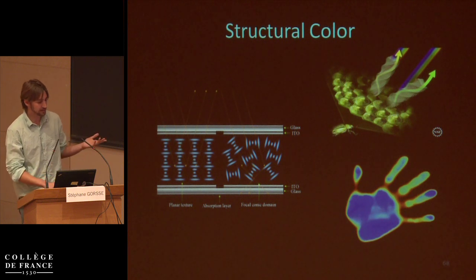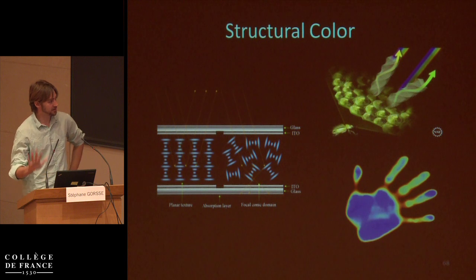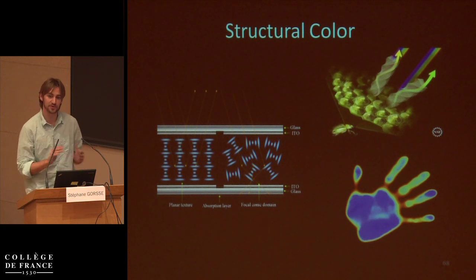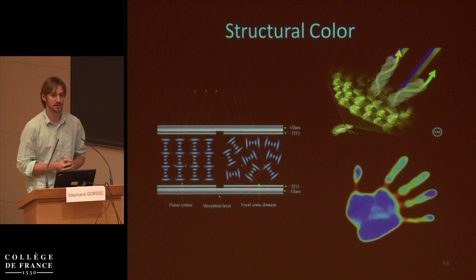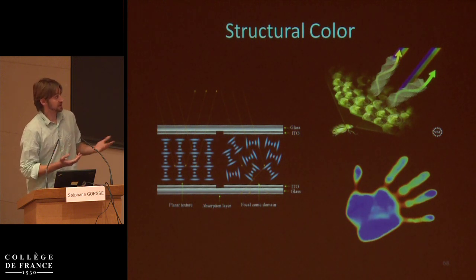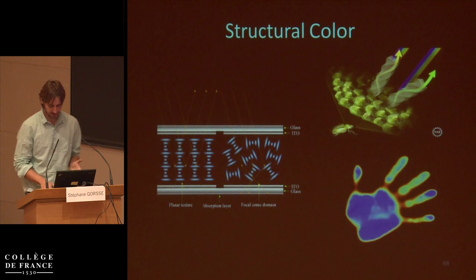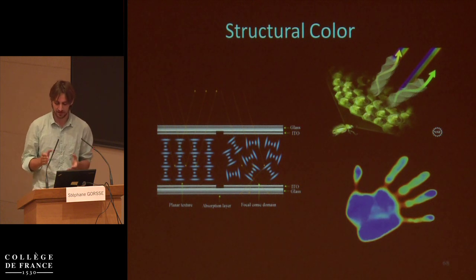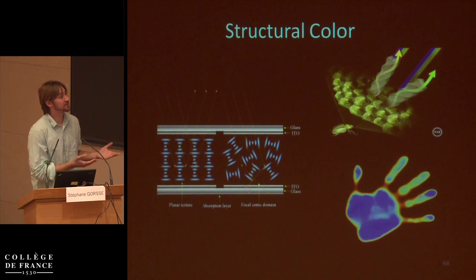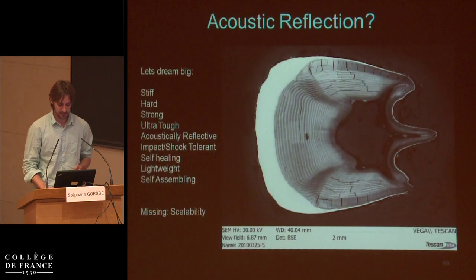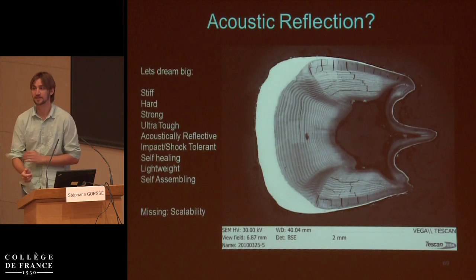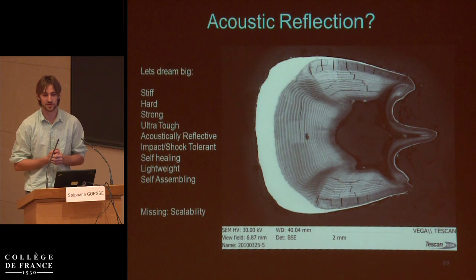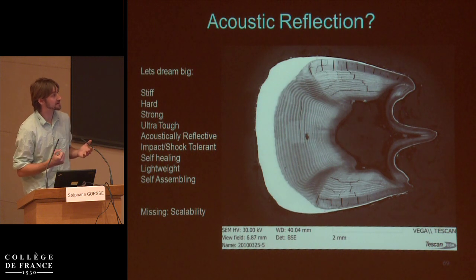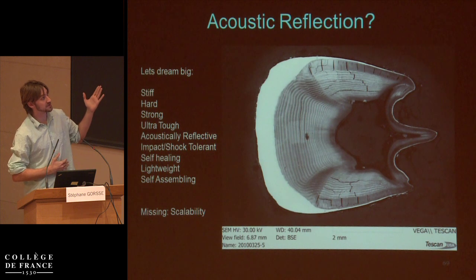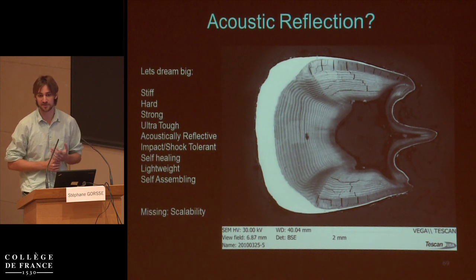And this is very analogous to these thermally changing cholesteric liquid crystals that you'll see, where as you heat it up, your thermal contraction or expansion will change the pitch and therefore the color. But similarly, in the same way that there's an analogy between photonics and phononics, there's an analogy between this optical phenomenon and an acoustic phenomenon. And so it's very likely that because of the stress wave induced by this severe impact, being able to resist the acoustic forces, not just the blunt impact, is very important for this organism.